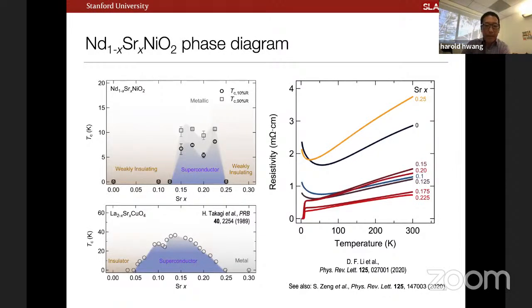Okay, and then our initial look at the phase diagram and the doping dependent structure was looking at this neodymium strontium system where we spent most of our energies. First statement is we see a dome of superconductivity. And I compare this with the 214 cuprate system, so it's rather qualitatively similar. What is different, though, is that we see weakly insulating behavior on either side of the dome, right? These are the raw resistivity curves, and really there's not that much of a spread. Let me also say that this was around the time of the first independent group working on the system. So this is from Ariando's group at the National University of Singapore, who had very similar lovely data.